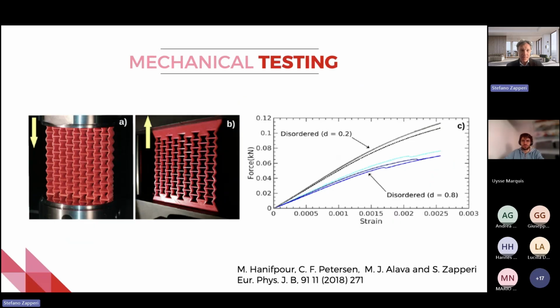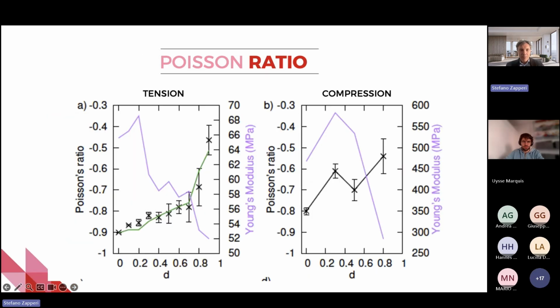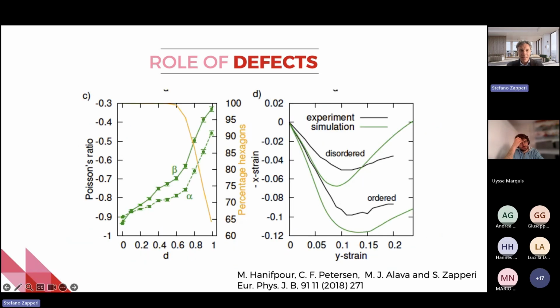Then we studied mechanical properties, both by simulation, in this case using this polymer physics model, and also by 3D printing this structure and doing mechanical tests. At the end, what we see is that for zero disorder, you get the nice auxetic behavior, Poisson ratio minus 0.9. As you add disorder, you change the Poisson ratio a little bit, so you lose a little of this nice auxetic behavior, but not so much. At some point, however, there is a big loss of this negative Poisson ratio, so the Poisson ratio becomes much larger. What we realized is that at this point you get topological defects coming into play. As long as you don't have topological defects, so you just wiggle a little bit, you still get the same kind of behavior.